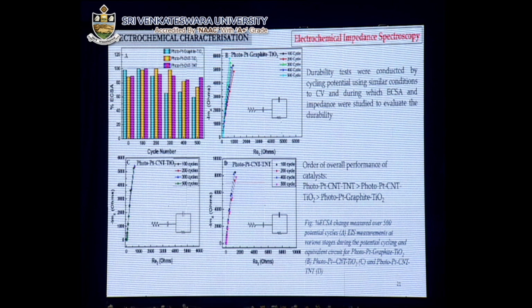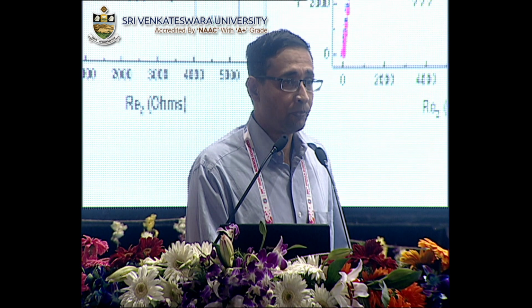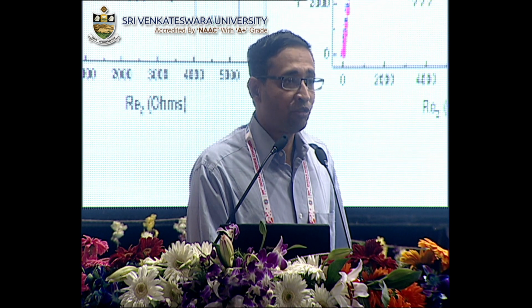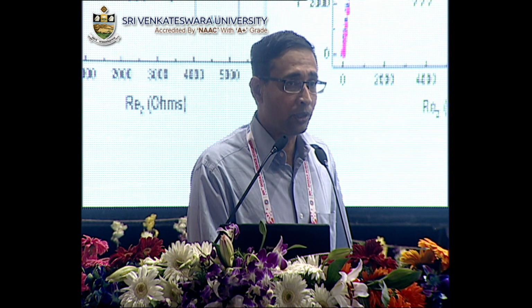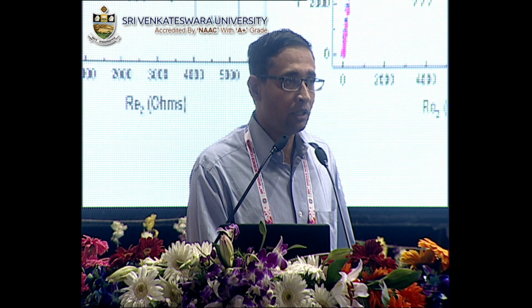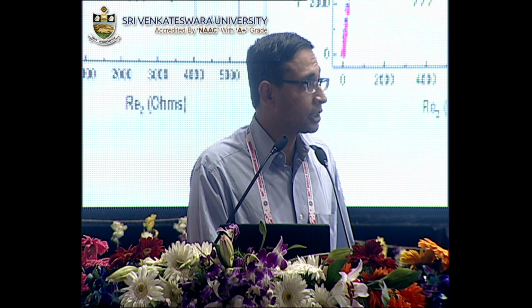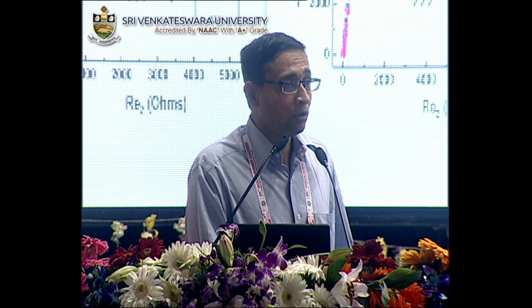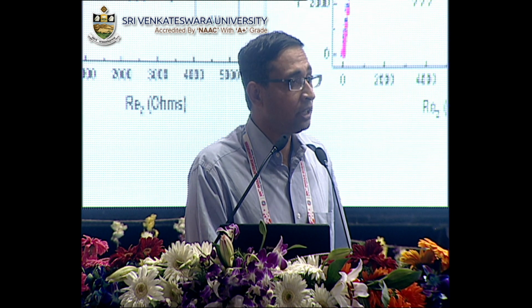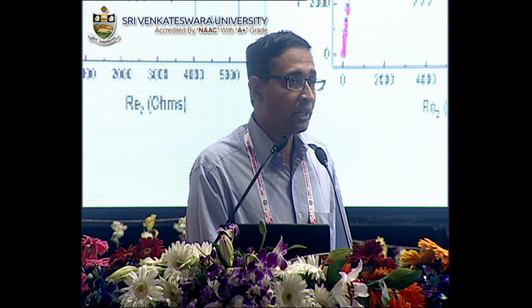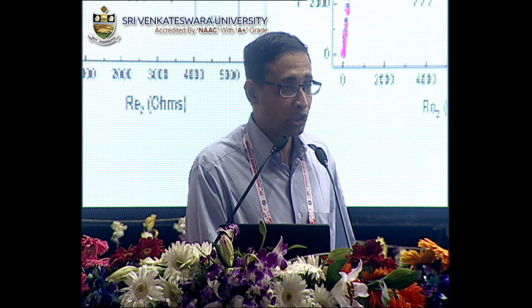So now the next step is to understand the durability of this electrocatalyst. We cycled the electrocatalyst for 500 fuel cell load tests, and we found that the material does not lose its strength even after 500 cycles of load test. Though 500 cycles is a little low as of now, the experiments are still continuing, and we have proved that this material will be a useful material for the future.